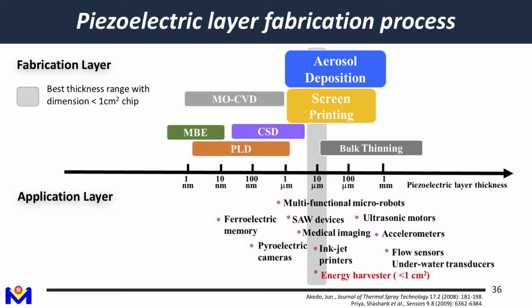Okay, so for small scale piezoelectric film deposition, on the top are different fabrication methods. For example, MBE is epitaxial if you want to grow single crystal material. CSD is the high performance piezoelectric PZT film based on the sol-gel process, that's texture aligned to the silicon axis of 100 or 110. And PLD is pulsed laser deposition, as mentioned. It can grow PMN-PT single crystal film.